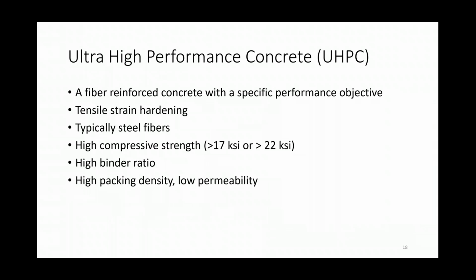Okay, so the next thing was ultra high performance concrete, UHPC. You've probably all heard about it because it's such a popular topic right now. It's essentially a type of fiber reinforced concrete. Usually the fibers are high strength steel fibers, and the UHPC is essentially a fiber reinforced concrete with a specific performance objective, and that performance objective is, well, it has very high compressive strength, more than 22 KSI is possible, which again is not so critical for decks to achieve, and it has low permeability, so very high packing density, low permeability, so that makes it very durable, and that makes it attractive for deck applications.